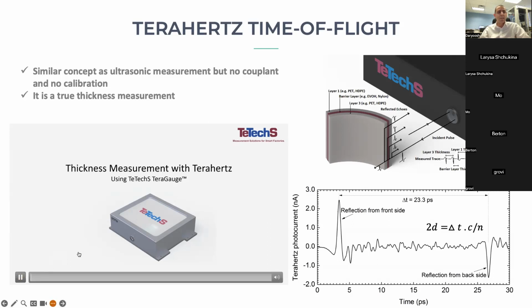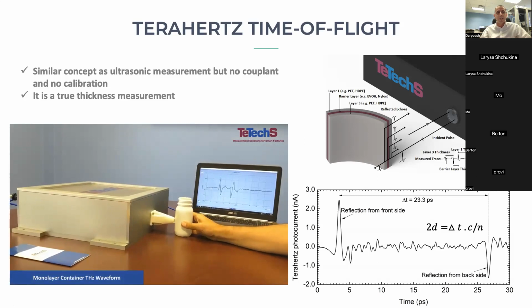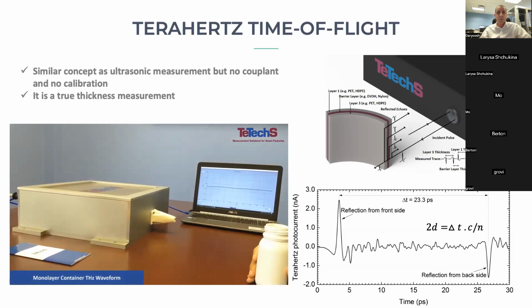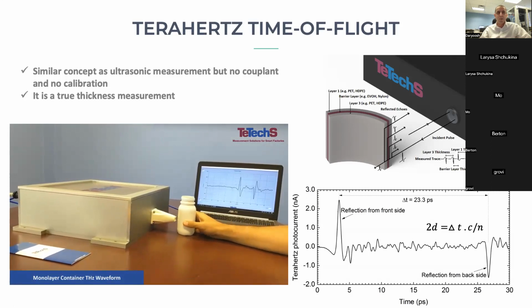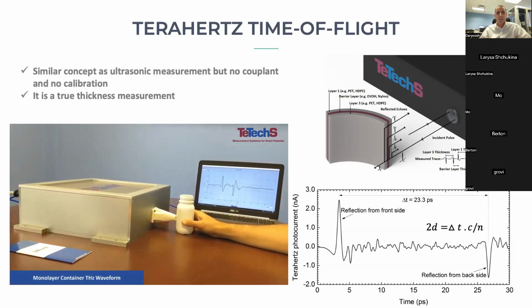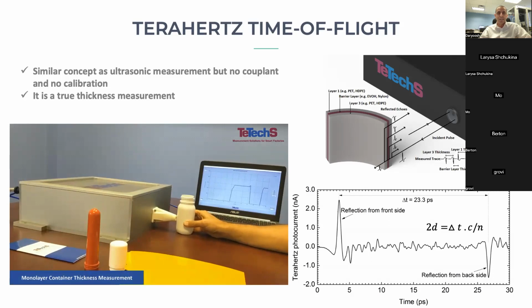So here is a video that basically shows the principle of that time of flight measurement, one of our earlier measurement systems, just as a concept. So you see the sample, which is in this case an opaque bottle, gets exposed to the terahertz light, and you get the echo from the front side of the spot you're measuring, and the other side. And then the system automatically takes the timing, and in this case also plots the thickness value at that spot. So that's basically, in a simple form, demonstrates the time of flight measurement using a terahertz time domain system.